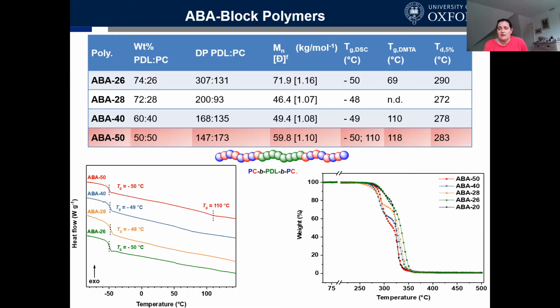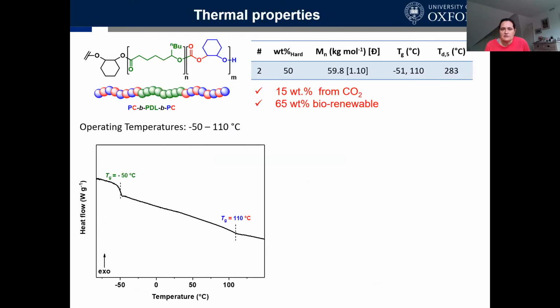Here, some thermogravimetric data showing you that the decompositions are typically beginning above 270 to 280. So it's got reasonable thermal stability, and it's got a reasonable processing temperature window. And that would typically be the temperature above the upper glass transition at 110 and prior to it decomposing. But that's very important if you make a new polymer, because you've got to be able to process these materials hot through extrusion or casting processes.